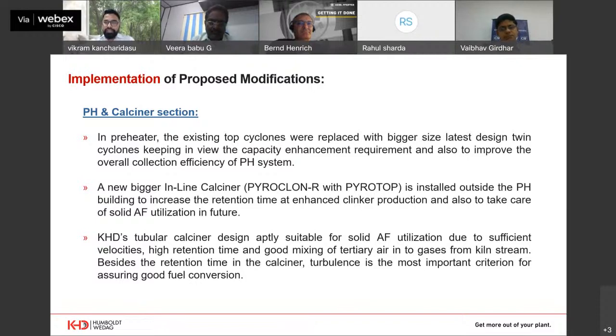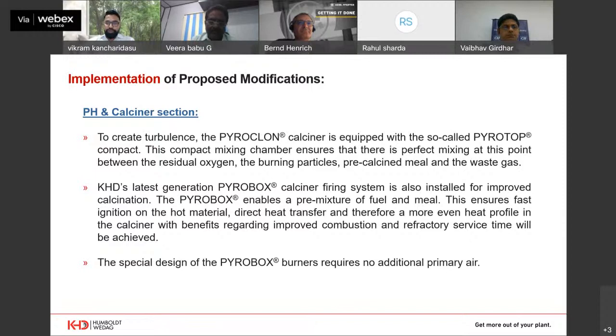And the second thing is that the kiln gases and tertiary air gases mixing takes place in the tubular calciner with the help of the pyrotop. This is a unique design in KHD calciners, where we have the pyrotop on top of the calciner, which takes care of the complete turbulence and the mixing effect, because the residual oxygen that is coming and also the burning particles, meal and fuels must be mixed well before going into the bottom cyclone. Sometimes we have the residence time, but without turbulence, we will not get the required combustion. So with this pyroclone with pyrotop design, we have the complete mixing effect, and before reaching the top cyclone, we will get the complete combustion.